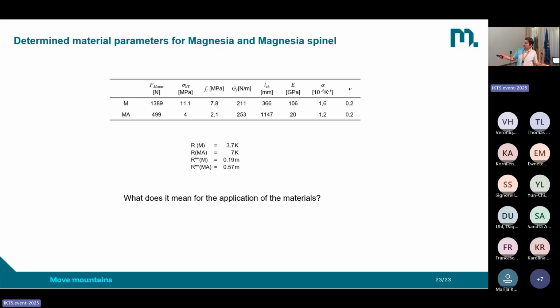Surprisingly, for the magnesia spinel refractory, this value is higher. It's 7 Kelvin. Why? Because of the influence of the Young's modulus. So Young's modulus is 5 times lower, roughly, for the magnesia spinel. If you look now on the Hasselmann parameter, which is proportional to the characteristic length, we see that this value is much higher for the magnesia spinel refractory. And this is in the end then a reason why this family of refractories is applied, for example, in the cement rotary kiln, where we need the flexibility of the bricks during turning of the rotary kiln, or for example, magnesia spinel bricks on the RH degasser, where we have this extremely harsh thermal shock conditions.